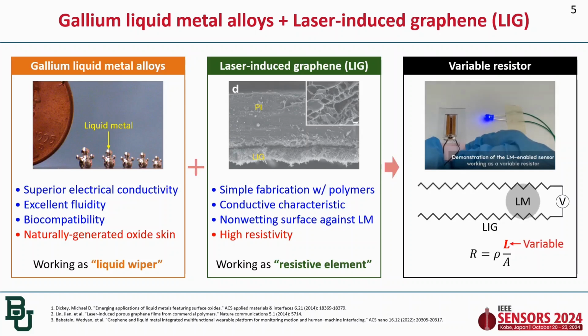In 2014, laser-induced graphene, or LIG, using a commercial polyimide and a CO2 infrared laser was reported. LIG can be easily made from polymers and has a non-wetting characteristic for gallium-based liquid metals. Additionally, it has high resistivity, making it a promising candidate as a resistive element in a variable resistor. Combining these two materials, gallium-based liquid metal and LIG, Babatian et al. developed a resistive liquid metal inertial sensor based on the principle of a variable resistor. When the liquid metal droplet moves between the two LIG lines by tilting, the resistance changes.